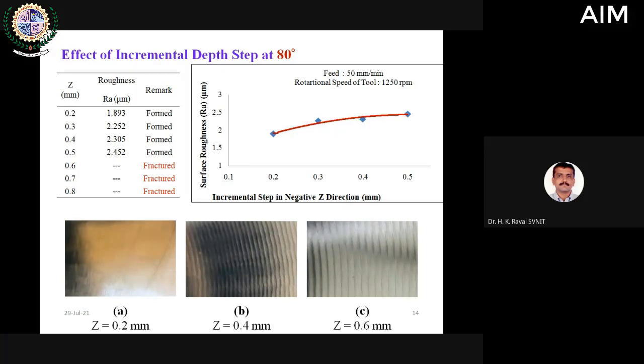That is, the surface roughness also will increase. At the same time, the chance of failure also increases. So one has to compromise between these two, and one has to optimize these two. Now, if you see this table, it is reported that a depth of forming beyond 0.5 results in a fracture. So one cannot get successful forming for the given dimensions, or I would say for the given thickness of the sheet, the given feed, and the given tool rotations, one could achieve successful forming up to the depth of forming of 0.5. Beyond 0.5 depth of forming, if it increases, the chance of success in forming is reducing.